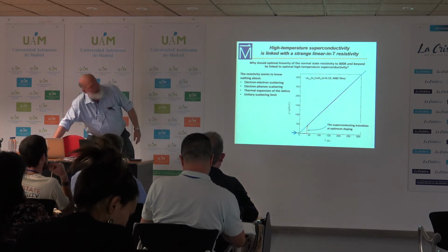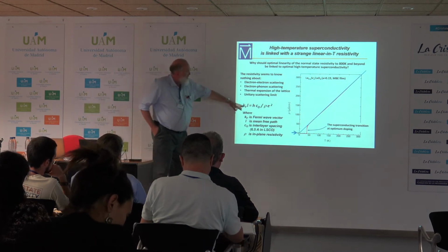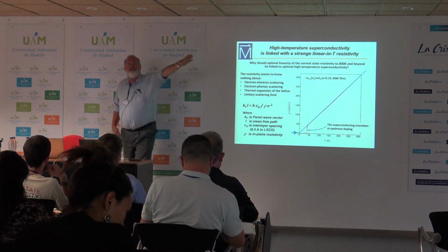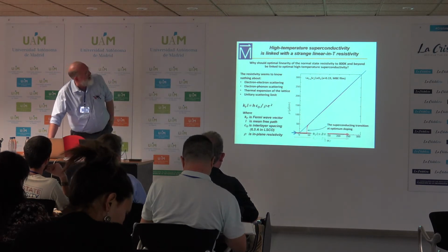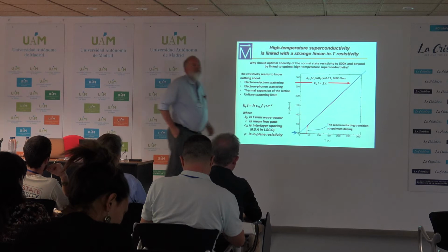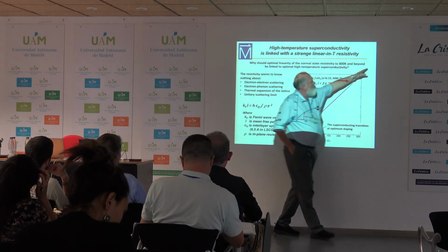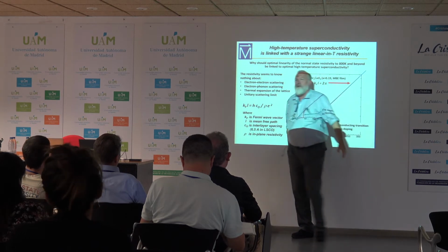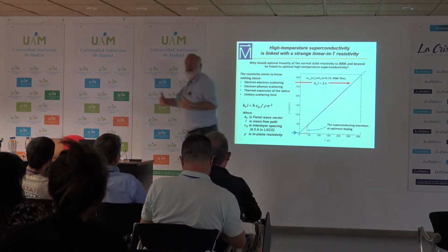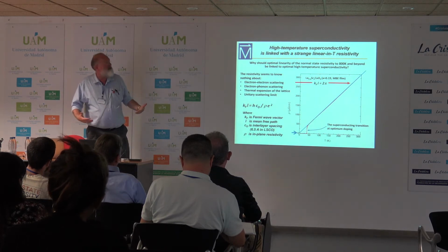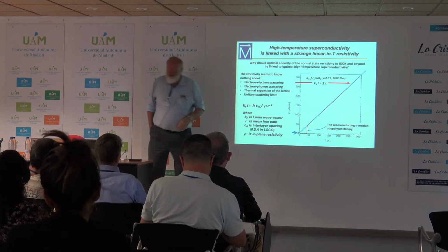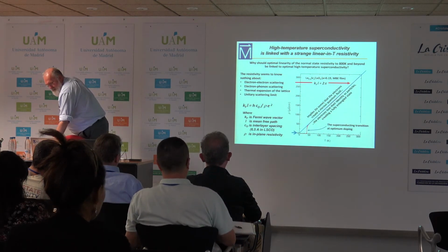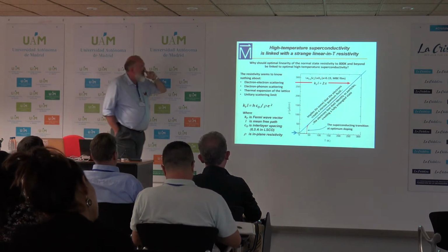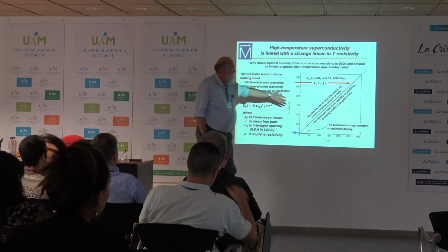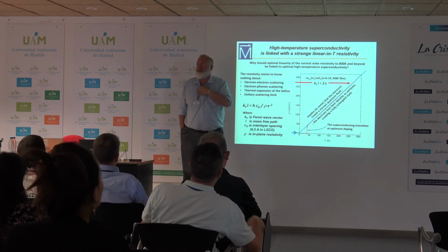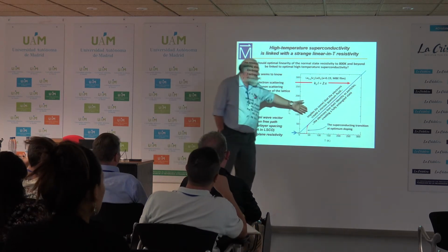And even the unitary scattering limit, where the electrons would have a mean free path that gets shorter and shorter as the resistivity goes up, eventually that mean free path gets to the point where it's the distance between atoms. So for any resistivities higher than this, and it keeps going up, your electron, if it exists as a quasiparticle, is scattering more frequently than off of every atom that it passes. And so this implies to some that the electrons create a viscous quantum fluid, as Tony mentioned, and then quickly moved on, which is the same strategy that I will adopt, to quickly mention but then move on.